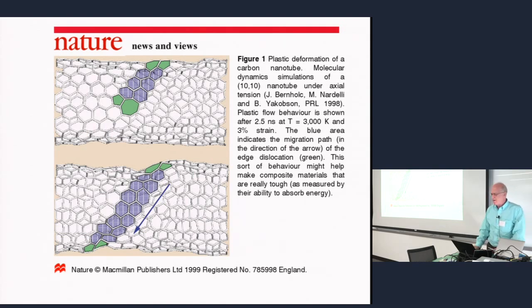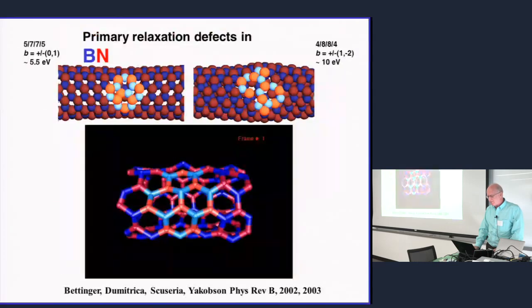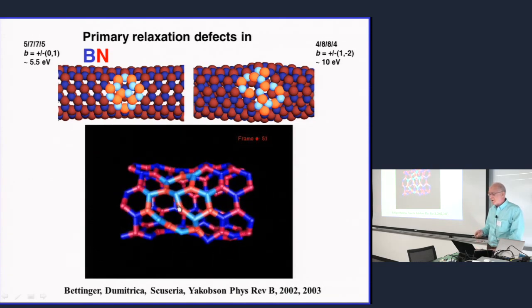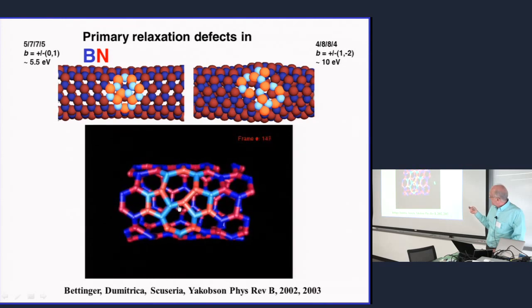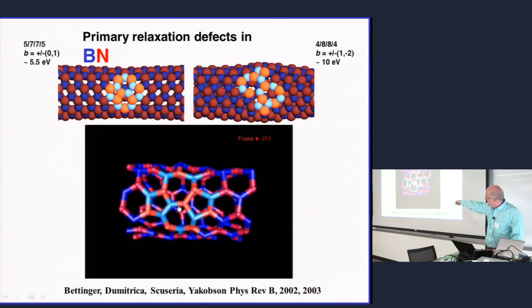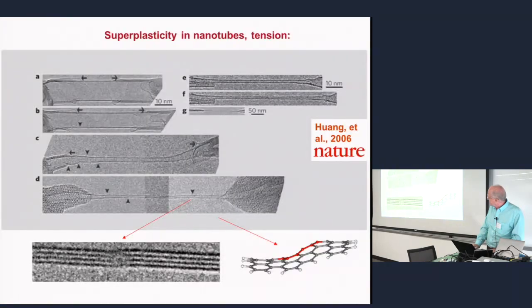So this was all very nice, and in theory it was correct. And I can show you this MD which we did later, just for one step. This is boron nitrogen, the same story, a BN nanotube or BN sheet. You see this bond rotating. This is at high temperature and under high tension, which is not easy to see, but I'm telling you, it's about 10% strain, and then it motivates this rotation because this defect elongates. So that's the mechanism of first yield, and this defect is responsible for initiation of yield, and of course at the same time it's a dislocation dipole, and dislocations are important.